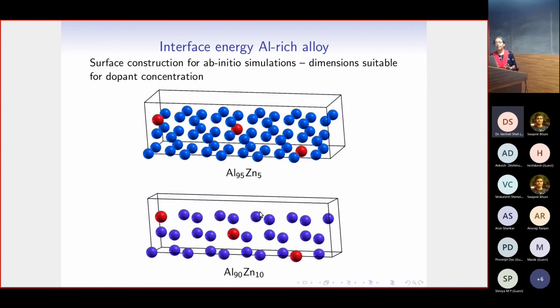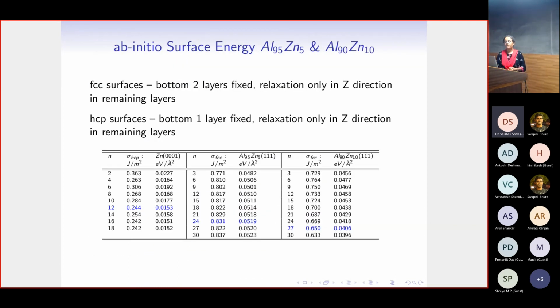Similarly, for the 90-10 now, we have to work with a different unit cell structure. And so this is smaller than the 95-5, and that always happens. As the dopant concentration increases, we can work with smaller and smaller unit cells. But the other way, as the dopant concentration reduces, we have to go to very large unit cells to be able to do the calculation. Okay, so we find the surface dimensions that would be suitable, and now with this we will perform the repetitions along the z direction to get the slab thickness. Okay. So this is what we do.